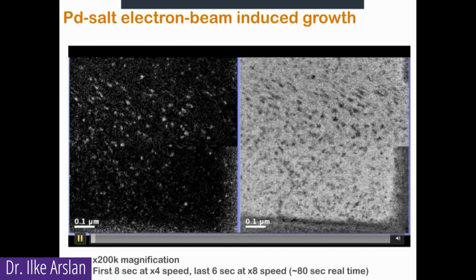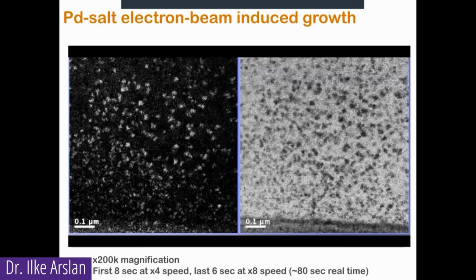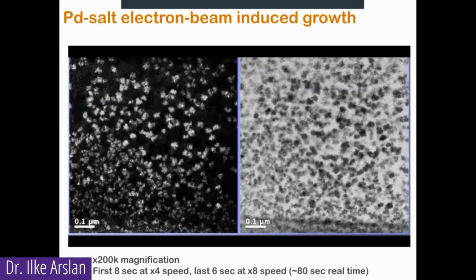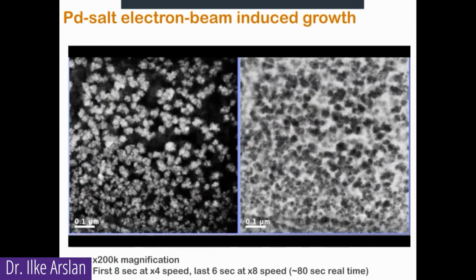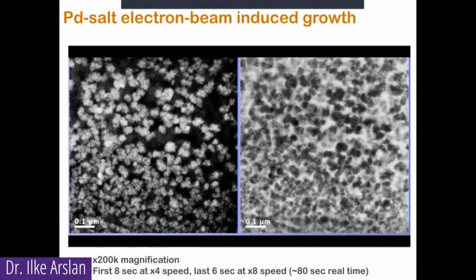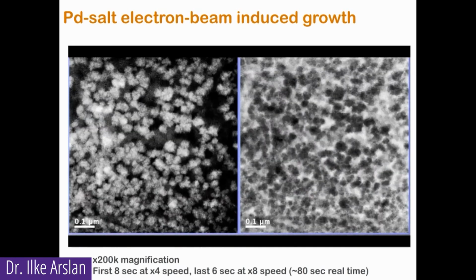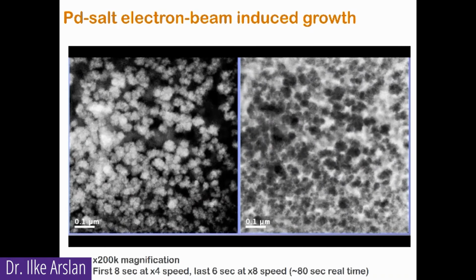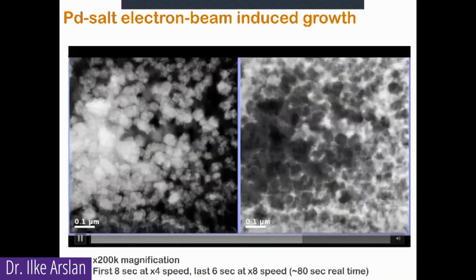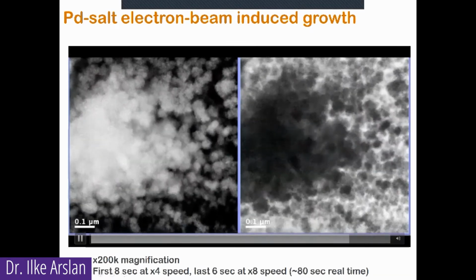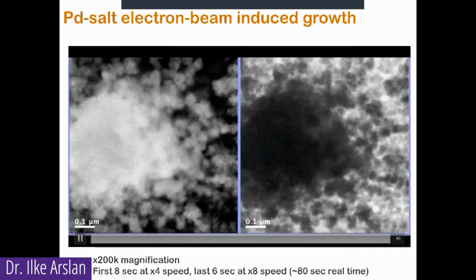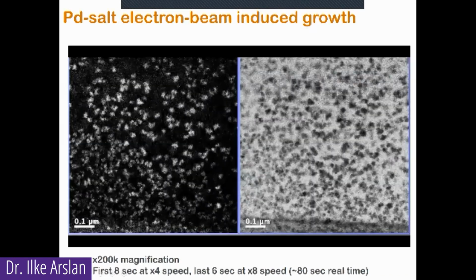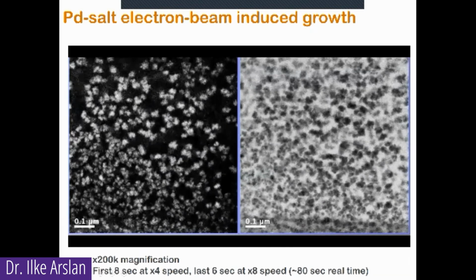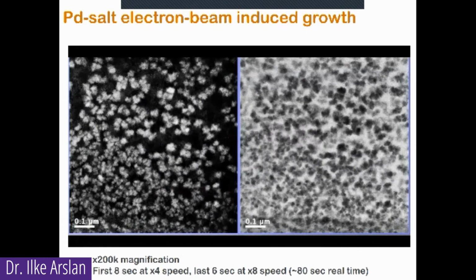And what you can see as we turn on the beam and take this movie, this is sped up by 8 times. It's an 80-second real-time movie. You can see that the palladium particles are growing in the solution. And they are moving around. You'll see this movement as the particles grow and clump together. So we're like, okay, this is what it looks like when you're just looking at the palladium salt solution.